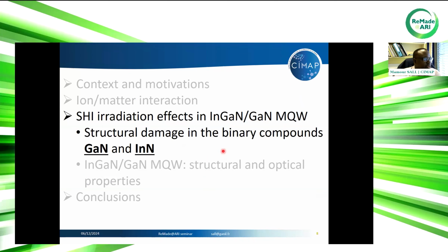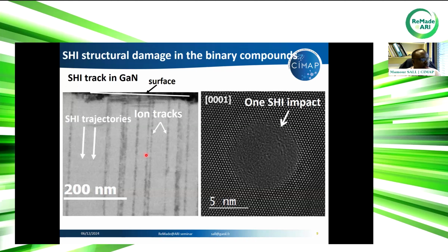So from this, I can maybe start presenting the results in our multi-quantum wells. But before presenting the results in indium gallium nitride quantum wells, I would like to show what happened in the binary compounds that make these multi-quantum wells. So the binary compounds are gallium nitride and indium nitride. These are TEM images of gallium nitride irradiated by swift heavy ions. On the left-hand side, this is a cross-section TEM image where we can see the sample from the surface to deep in the volume. Each dark line you can see here is an ion track. Each single ion will create this modification of the material structure. And these are the tracks I talked about before.